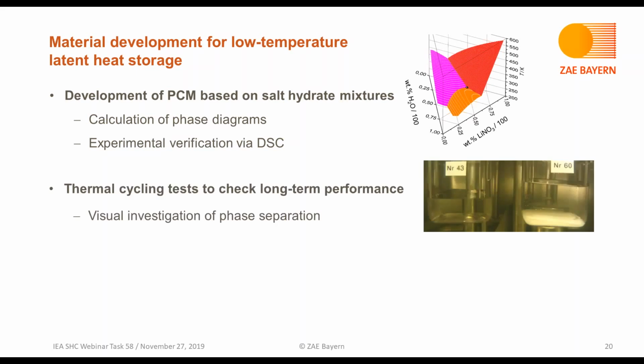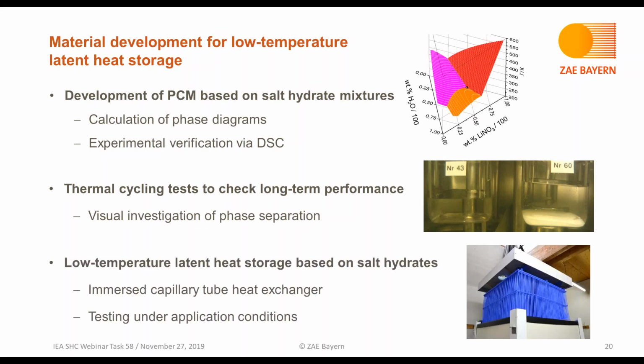The second step would be to perform thermal cycling tests in order to check the long-term performance of these materials. And as you have seen, it is very useful to visually investigate the phase transition, and thereby being able to investigate possible phase separation processes. And in the end, this material development can be transferred to the concept of low temperature latent heat storage using an immersed capillary tube heat exchanger. And also at this storage level, it's important to perform testing under application conditions to ensure the long-term performance of these materials.